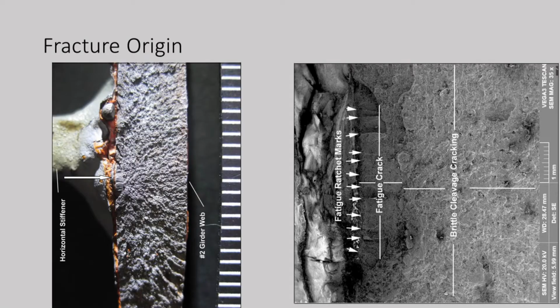Optical view of this detail, a little greater magnification. I think you can see these chevrons here a little bit clearer, but the point of interest is this little thumbnail detail, and that seems to be the point where the fracture has originated. So anyway, what we did as part of our failure analysis is we cut that area out, and then we put it into a scanning electron microscope.